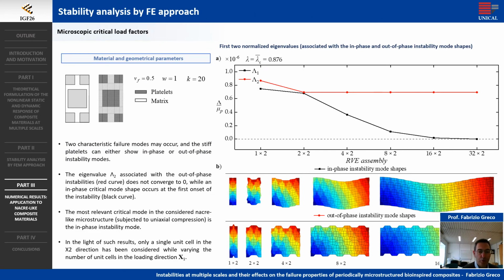The results obtained by performing a microscopic stability analysis carried out for increasing assembly unit cells are now illustrated for the composite characterized by shear modulus contrast K equal to 20, platelet volume fraction equal to 0.5, and platelet aspect ratio W equal to 1. The picture illustrates the behavior of the first two instability modes and associated eigenvalues as a function of the RVE assembly size, increasing in the horizontal direction with a geometrical progression and a fixed number of 2 unit cells in the vertical direction. A fixed stretch ratio coinciding with the macroscopic critical stretch ratio is considered.